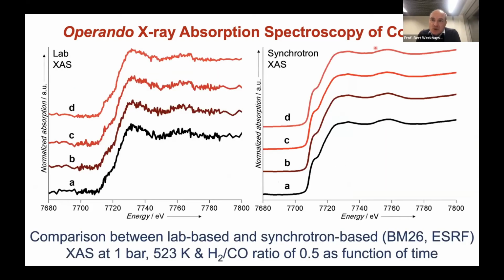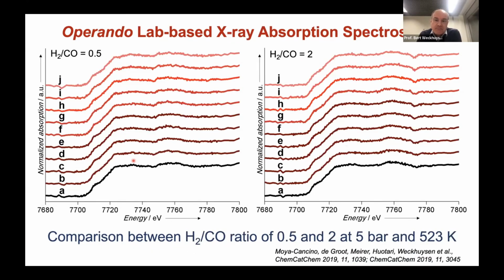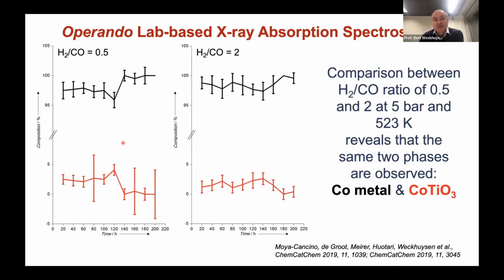So we used again our cobalt titania catalyst, which I described before. I show you here lab-based XAS and synchrotron XAS. No doubt, synchrotron has a better signal to noise ratio, here it is more noisy, but you can record such a spectrum. You can measure it at, for example, 1 bar. You can also bring it to higher pressure, up to 5 bar. And here I show you different ratios of hydrogen to CO for the lab-based. Clearly, you can now measure lab XAS under operando conditions of a catalyst.